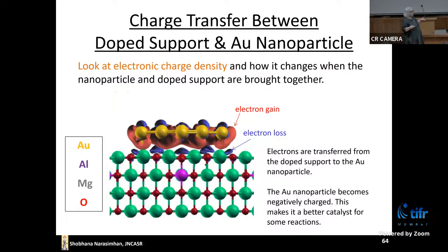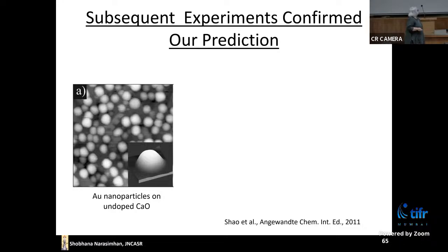And basically what happens is that when you put these aluminum atoms, they donate electrons to the system. These are transferred to the gold, and then the gold prefers to flatten out for electrostatic energy reasons. Okay, so does this really work?